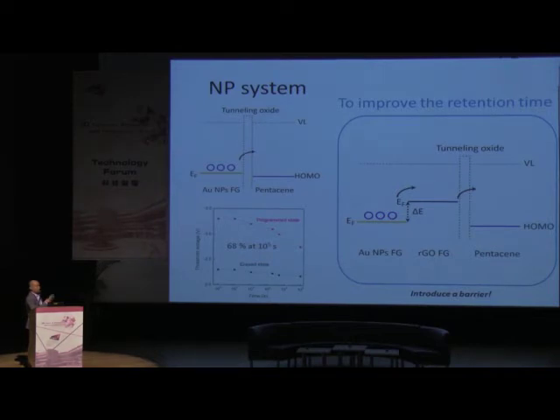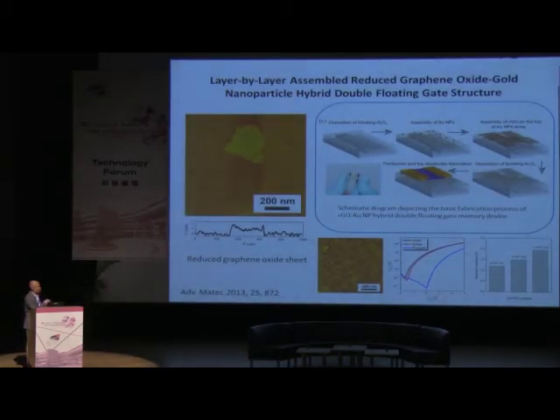So you have a double barrier, and the retention time is enhanced twice. This is how we make the device. We pick a simple PET substrate and functionalize it with negatively charged nanoparticles, and then we add another polymer which is positively charged, PAH, and fill up the graphene. So these are all layer by layer by charges. These charges attract each other and stick together as a whole device.